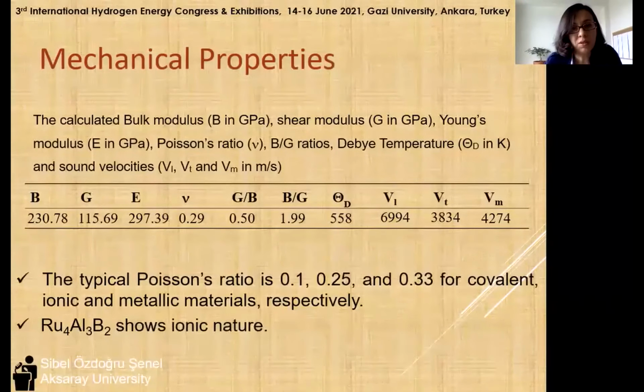The typical Poisson's ratio is 0.1, 0.25, and 0.33 for covalent, ionic, and metallic materials respectively. The Poisson's ratio is 0.29 for ruthenium-4 aluminum boride, so the compound shows ionic nature. About the Debye temperature, all vibration modes are active.